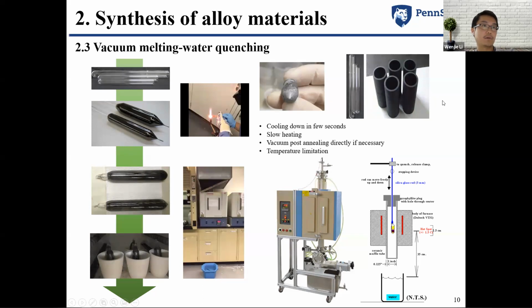When we were dealing with p-type skutterudite materials, since there is a lot of iron content in the compositions, even with this graphite coating, sometimes we still have crack issues due to the reaction between the materials and the quartz tube. In that case, we can put additional graphite tubes inside the quartz tube and load the materials inside the graphite tubes to further avoid this reaction between the tube and the materials using this method.